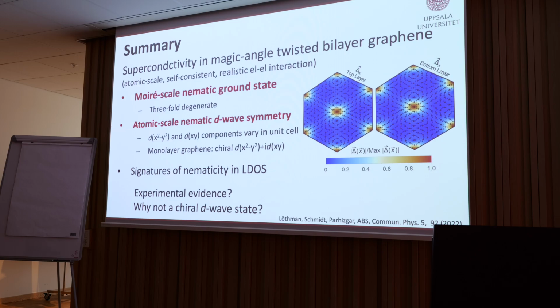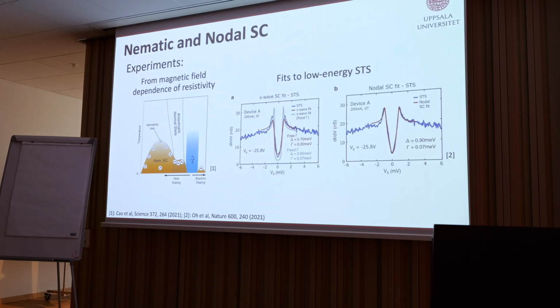But first, to put this in context of what other people have done. We already saw some very nice work this morning, and you saw some of these plots. There seems to be data from experiments pointing to a nematic state. This shows the nematic axis in the different superconducting domes, extracted from the magnetic field dependence of the resistivity. And there are also fits to STM data trying to fit the S-wave and the D-wave state. There was a discussion about which gap it fitted, but in the end I think a nodal state was proposed either way. And clearly, if you have a nodal structure, it's unlikely to be a homogeneous S-wave state, right? So based on this, it's likely nematic and likely a nodal superconductor.